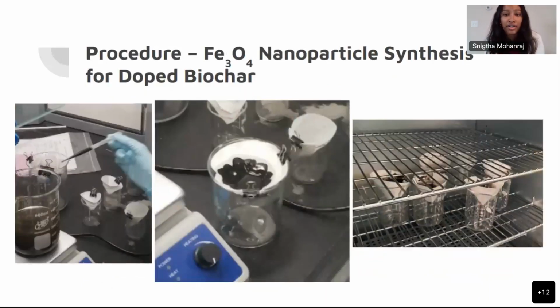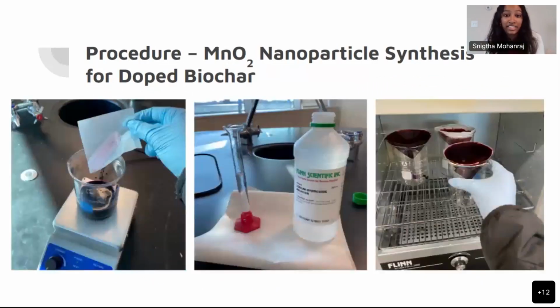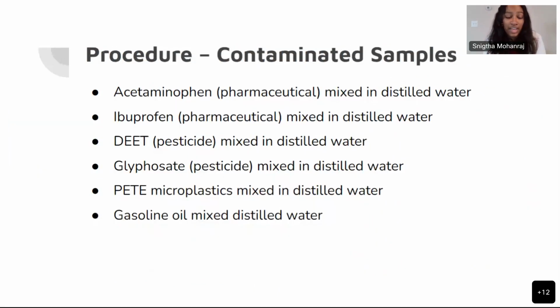So these pictures show the iron oxide nanoparticle synthesis for the doped biochar, and these pictures show the manganese dioxide nanoparticle, again for the doped biochar. And then the contaminated samples, I tested 6 different contaminants. The first 2 were acetaminophen and ibuprofen, which are pharmaceuticals. The next 2 were DEET and glyphosate, which are pesticides. And then PET microplastics, since PETE is the most commonly used form of plastic, and then gasoline oil.